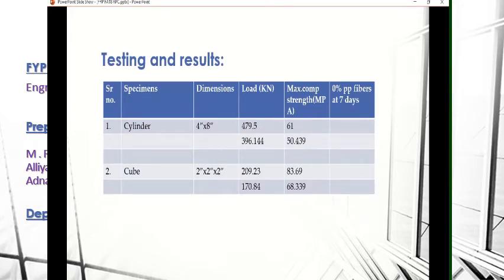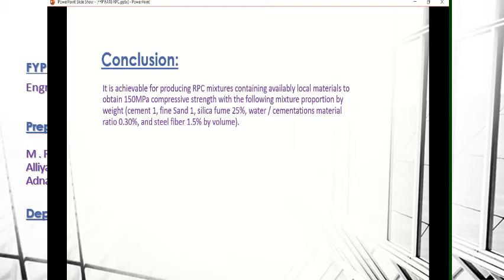The specimens we have tested up till now are cylinders and cubes, and we have checked their maximum compressive strength. The strength was very good in terms of the results we have got from the literature review. The conclusion we have drawn is that it is achievable to produce RPC mixtures containing locally available materials to obtain 150 megapascals compressive strength with the following mixture proportion by weight: